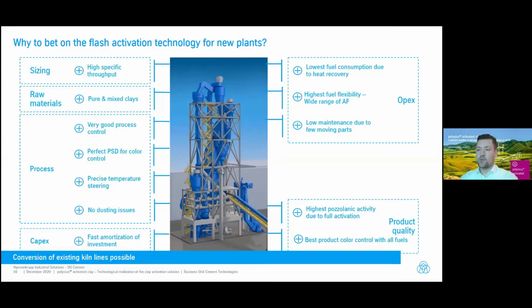So basically, we are also able to build rotary kilns, for sure, we are doing so since years. But in this case, we really don't see an advantage of the rotary solution because we could show that the costs are nearly the same. So this is not a big differentiator at the end. And we see that the product quality of the flash activator is simply better. So we are saying typically we would like to go for a flash activator when speaking about greenfield plants.